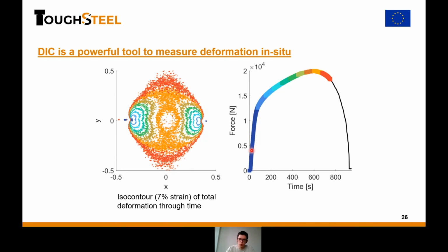And so each color corresponds to a point in time on my force. Well, here it's force time, but it could be force displacement. And so, for instance, if you take the light blue isocontour here, we can see that the deformation was localized here close to the notches. And why I do this is to check if the criteria for the validity of the method was met for each of my tests. One of the criteria is that the ligament must be fully plastic before crack initiation. And since crack initiates about at the maximum force or a bit later, here I can check that the whole ligament was plastic right before the crack initiation. So this is the first thing you can do.